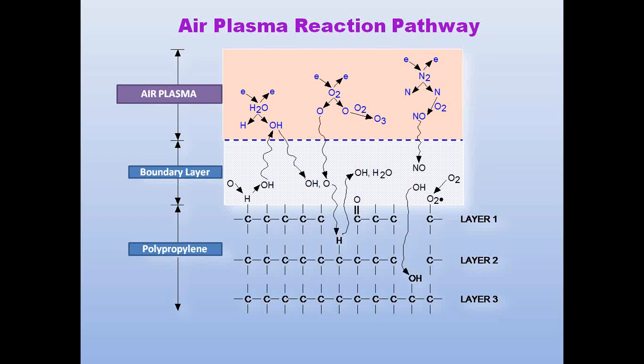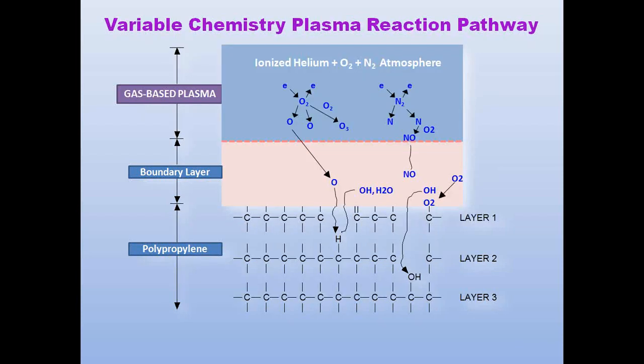If we go to a gas-based or gas phase plasma, also a variable chemistry pathway exists. In this case, we're representing a plasma forming inert gas, helium in this case, with reactive components of oxygen and nitrogen in atmosphere. You can see that, again, the same type of depth of treatment, the same type of free radical effect takes place. But in this case, you're allowed the opportunity to change the surface chemistry relative to the chemistry of what's going to be applied to that surface.